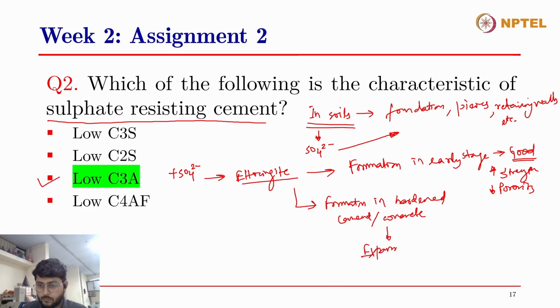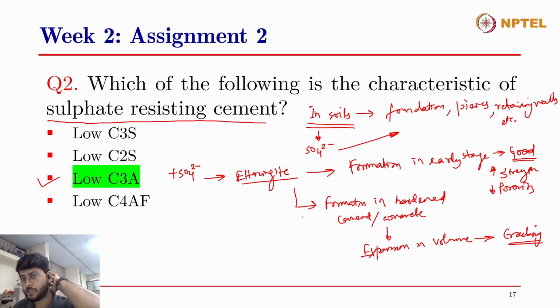Due to this expansive force caused by the formation of ettringite, the ettringite wants to expand inside the concrete, and that in turn creates a tensile stress inside the concrete matrix. As we know, concrete is weak in tension, therefore this expansion in volume will lead to cracking. So ettringite formation at an early stage is good for us. It increases the strength and reduces the porosity, but when it is formed in a hardened state, it leads to expansion in volume and further cracking in the concrete structure.